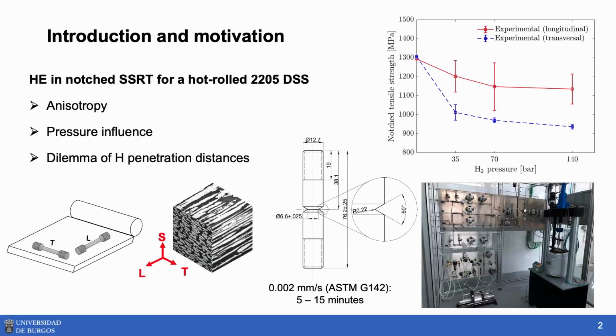Everyone is tired, so I will skip the classical motivation and even the outline. These are the experimental results that we are going to interpret and use to build a kind of predictive model. We are studying a 2205 duplex stainless steel in the hot roll condition. As you can see, we have a strong anisotropy because the austenitic phase is elongating along the rolling direction. We are following the ASTM G142 standard, and we are choosing the notched tensile specimens.